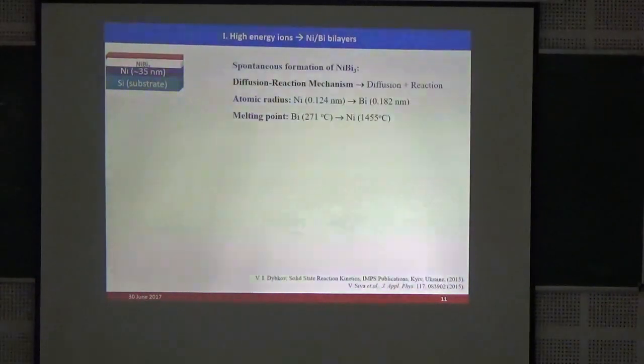So, in the case of ion mixing, let me start with the high energy ions. Before getting into the details of ion mixing with high energy ions, during deposition itself we have seen a spontaneous formation of the NiBi3 layer. It was a very interesting thing. For the first time, we have observed it, and it was published in this chapter. The spontaneous formation of NiBi3 happens due to a mechanism called diffusion reaction.